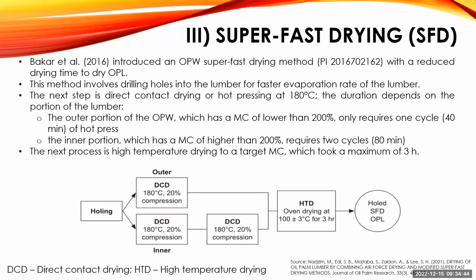For the inner layer, there are 2 cycles of direct contact drying, because the inner has a much higher moisture content, so it requires one more drying cycle. After both direct contact drying cycles, the oil palm lumber will be subjected to oven drying, the high temperature drying in an oven at 100 degrees Celsius for 3 hours.